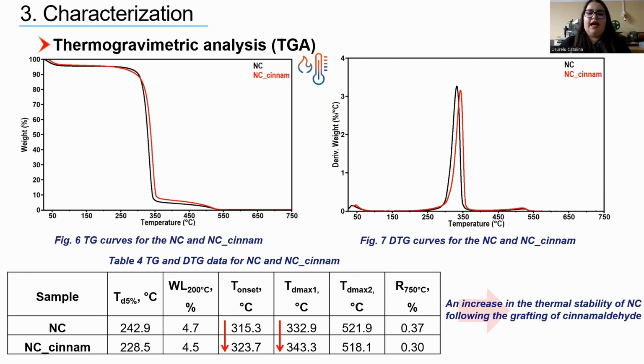The thermogravimetric analysis showed that the functionalization of nanocellulose with cinnamaldehyde led to an increase in the thermal stability of nanocellulose, which was observed by an increase in the onset degradation temperature by around 8 degrees and an increase in the temperature at the maximum degradation rate by about 10 degrees. This may be attributed to the aromatic rings from the structure of the nanocellulose modified with cinnamaldehyde, which are known to possess a better resistance to thermal degradation.